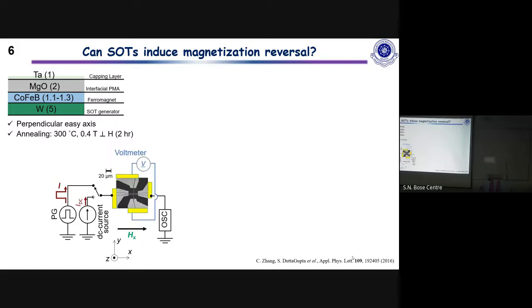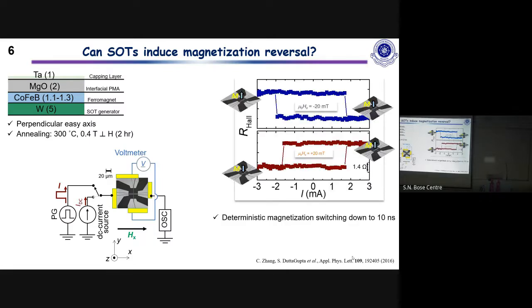So this is the device that we made. This was made using photolithography, and this is the measurement scheme. What we actually do is we first saturate the magnetization out of the plane of the board by using a magnetic field, and then we pass an electrical current, and we detect the direction of the magnetization by using the anomalous Hall effect, which is the transverse voltage in this joint. So this is our experimental result. We measure the anomalous Hall resistance as a function of the current which is flowing through the channel. Starting from a down configuration of magnetization, as we sweep the current, we see that we can deterministically switch it from down to up, and we can also do it from up to down and vice versa.